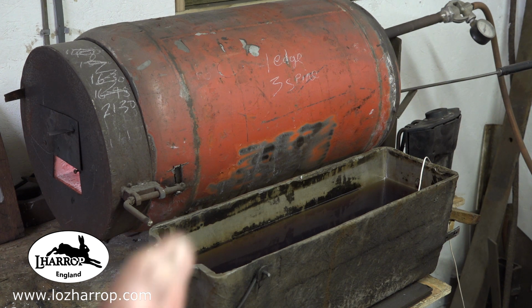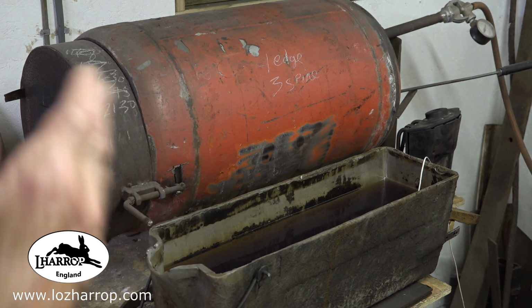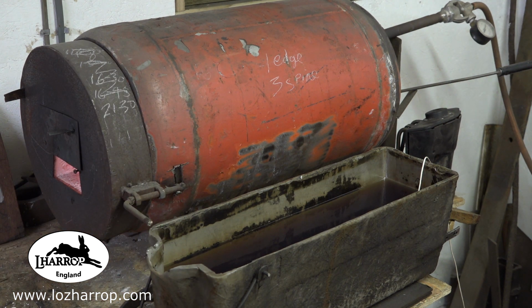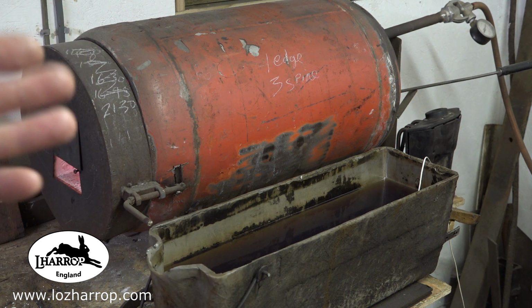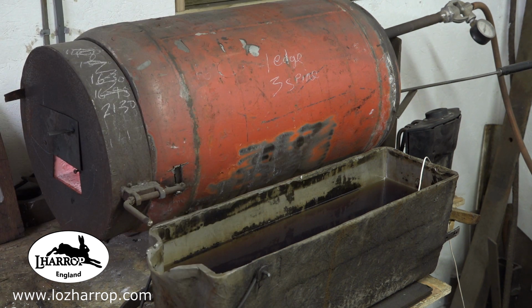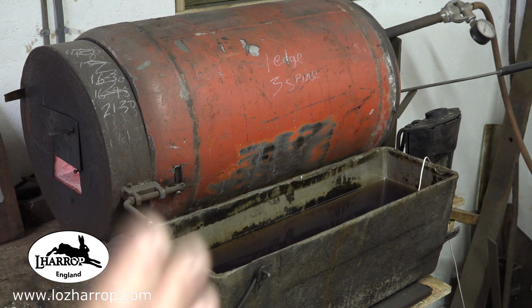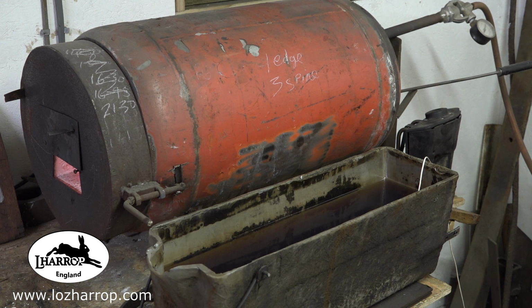But I know that temperature on that steel will give me a good hard edge. As you saw, going right back to the beginning, when we did the quench and break test, you saw the grain, which was a lovely grey, fine grain. Quenched, it was non-magnetic, so we're just above that, which should give me a great edge. We're going in now. Let's get it done.